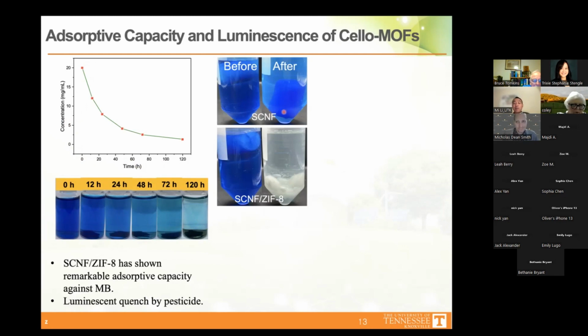Okay, so here is another picture, and you probably want to argue, well, it's a combination of the nanocellulose and MOF. How can we tell? How can you assure me it's not the function of your nanocellulose? Maybe that one can play the role of absorption as well. So in order to rule out that possibility, we threw in just a pure nanocellulose, and this is a methylene blue solution, and this is a pure nanocellulose. You can tell it does show a little bit of absorption, but not that much. And on the bottom, we put the hybrid nanocellulose with the MOF, and it becomes a very clear liquid.